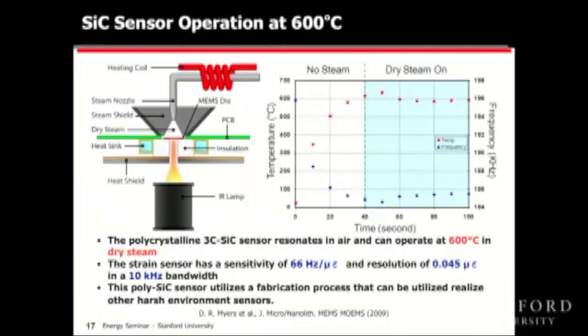So this device was subjected to temperatures as high as 600 degrees C. The backside of the sensor was irradiated with an IR lamp. It was driven with low temperature electronics at this point. We did this separately. We didn't have high temperature electronics to interface with the sensor, but we used an IR lamp to heat this up to 600 degrees C.